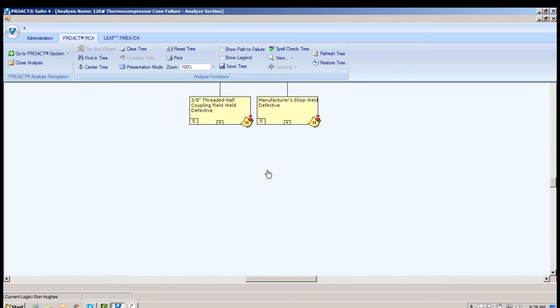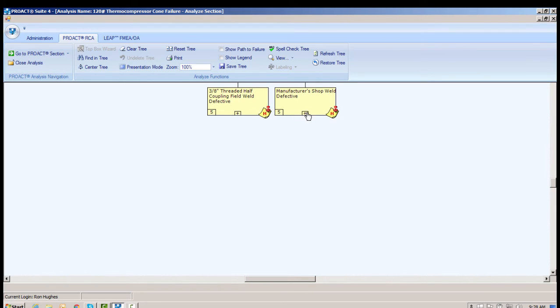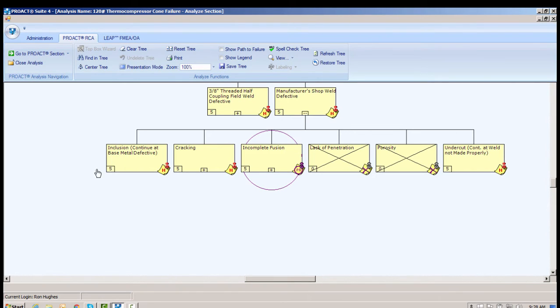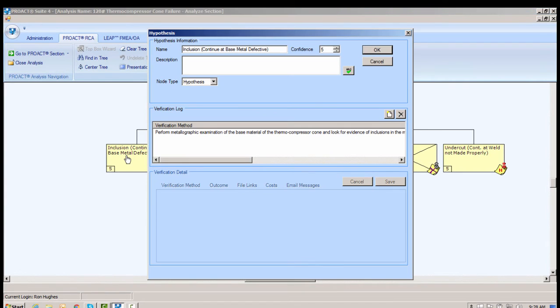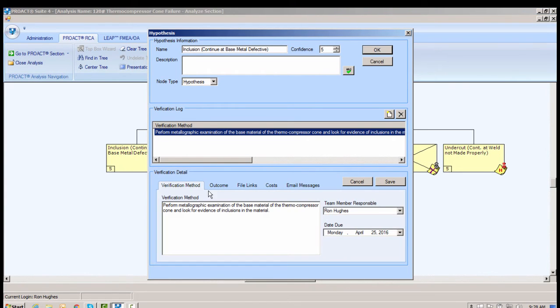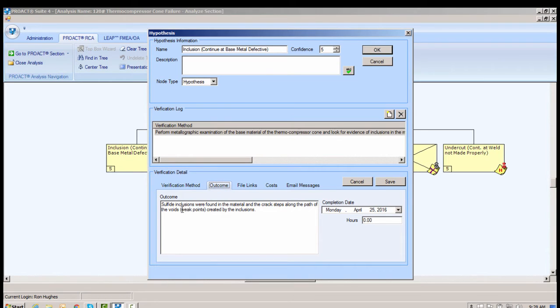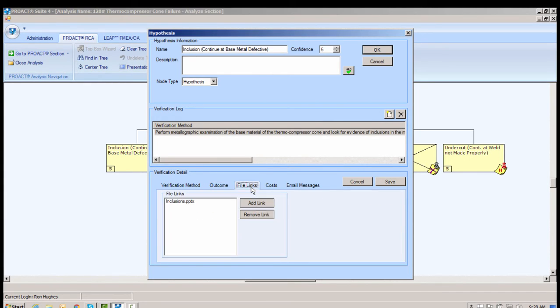Now let's go look at the manufacturer's shop weld. Again, we have the same welding defects: inclusions, incomplete fusion, lack of penetration, porosity, undercut, and cracking. Now notice over here we got inclusions, continued base metal defective. Now we do the metallographic analysis and we see the inclusions. Sulfide inclusions were found in the material, and the crack steps along the path of the voids, that's the weak points created by the inclusions.